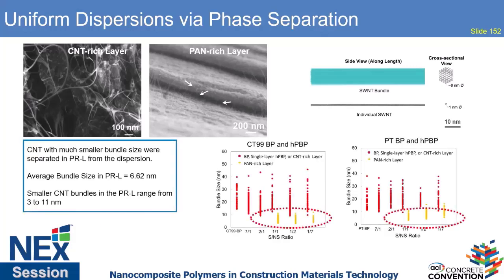And we've done some analysis on this for different nanotubes, different polymer systems, and what you can see very clearly is that in that nanotube-rich layer, again, you have a very heterogeneous mixture of size of bundles, but inside that polymer layer, every time you get a much more uniform distribution of the nanomaterial. And we've studied this for a bunch of different polymer molecular weights, and we can actually see a very nice correlation between that. And we've published a bit of work on it to show that basically it's related to the free volume in the polymer.